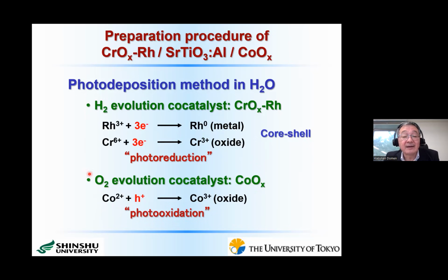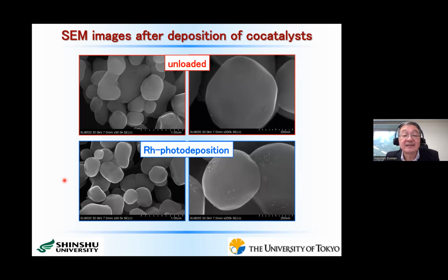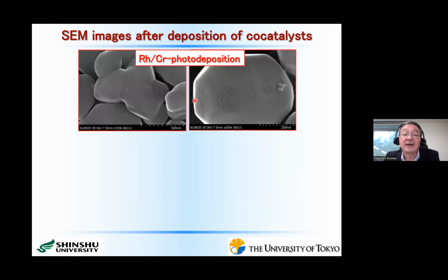So through this construction of the co-catalyst, here I show the change of the features of our photocatalyst. This is a SEM image of unloaded aluminum-doped strontium titanate. As you see here, this is a very well crystallized particle, but there exist many different facets on this surface. Then, after metallic rhodium nanoparticle deposition by the photoreduction method, you see only some limited facets where these small particles exist. Then, even after we coated this metallic rhodium with chromium oxide, again by a photoreduction reaction, we still observe this kind of particles on some limited facets.